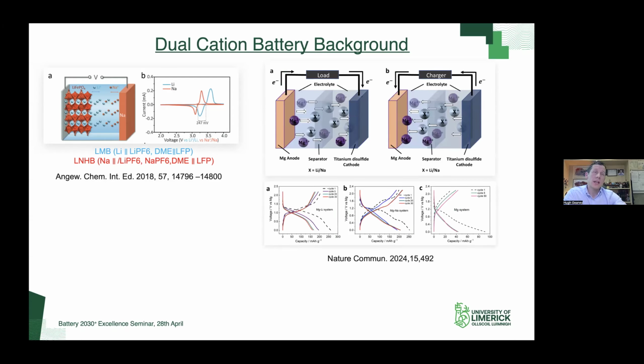The system that is most linked to what we have looked at is work from KIT more recently, in 2024. They chose a magnesium anode and titanium disulfide, which is very much a classic cathode system. They had a range of different systems at the electrolyte scale: a pure magnesium electrolyte, a magnesium sodium electrolyte system, and a magnesium lithium system. The thing to note straight away from the electrochemical response is that they're different. You have voltage profiles clearly showing different features over the same potential range, 2.4 to 0